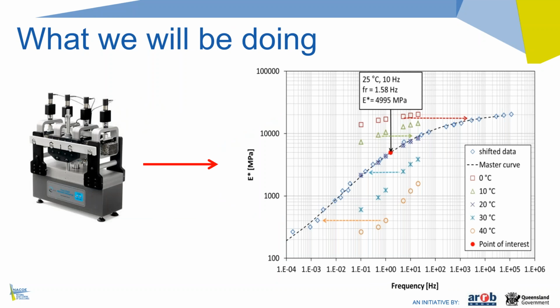What we're proposing to be doing in the future is run flexural modulus tests in a 4-point bending setup as shown on the left hand side of this slide, and we'll be testing at different temperatures and different load frequencies to get results as shown on the right. So the graph on the right shows results obtained at different temperatures from the flexural modulus test. So every marker, there's different color markers there. The markers at the bottom are from tests run at 40 degrees C and different frequencies. Then just above it is the results at 30 degrees C, different frequencies, and so on until 0 degrees.